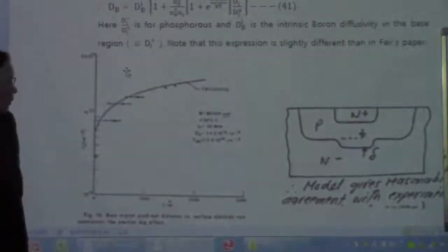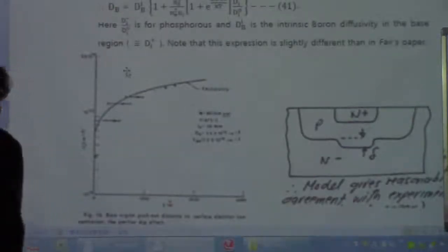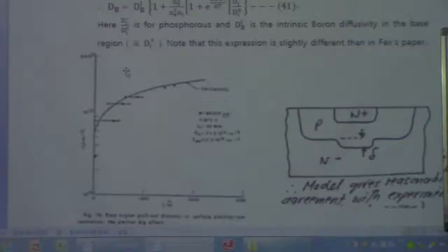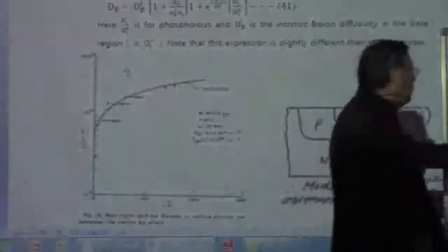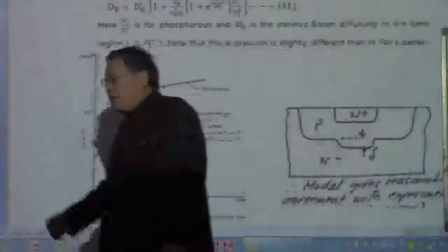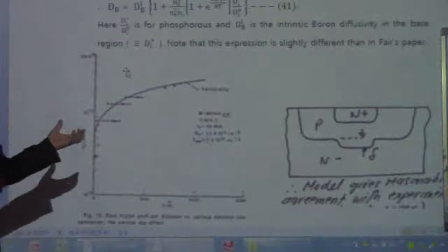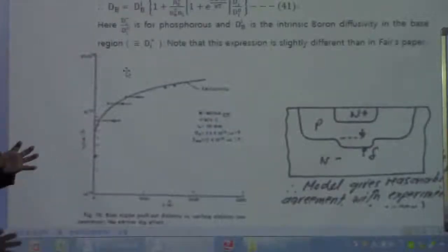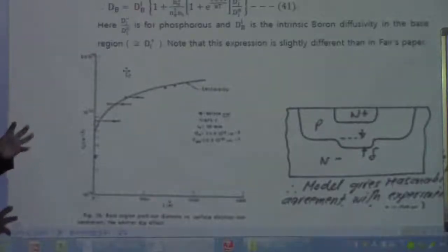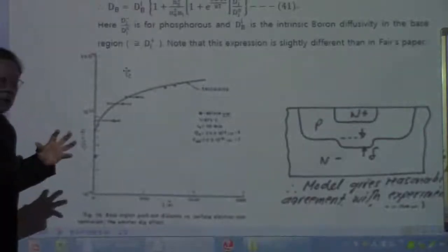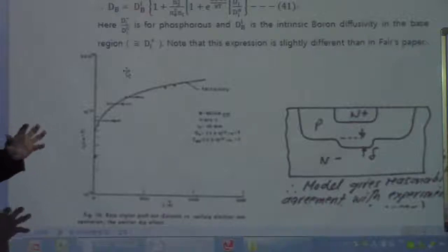So the model that we generated is based on the vacancy model, and especially for the phosphorus, we realized that it does have the doubly negatively charged vacancies. That is important. And then in a heavily doped case, by the dissociation reaction, it should have the enhancement of the V minus concentration, right?